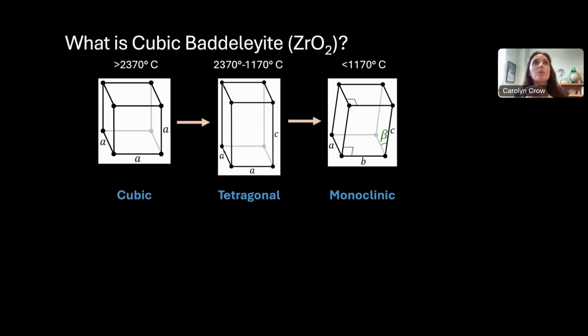Why are we interested in looking at the baddeleyite? Well, there's been a lot of talk about cubic phase heritage in zirconia on the moon and also in terrestrial impact structures. So what is cubic zirconia and why are we interested in it? Depending on the crystallization temperature of zirconia, it will have an initial cubic structure if it's crystallizing at really high temperatures above 2370 degrees C. If it's crystallizing above 1170 degrees C, but below that cubic structure, we will have tetragonal. And if it's crystallizing at normal magmatic temperatures, less than 1170, we will have a monoclinic structure. So understanding the structure of baddeleyite when it forms can give you some indication of the crystallization temperature.